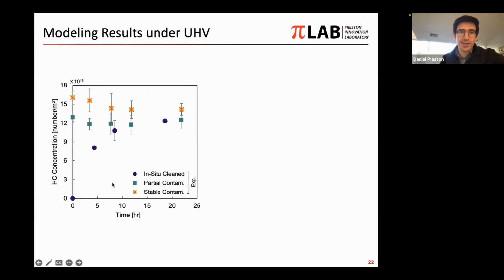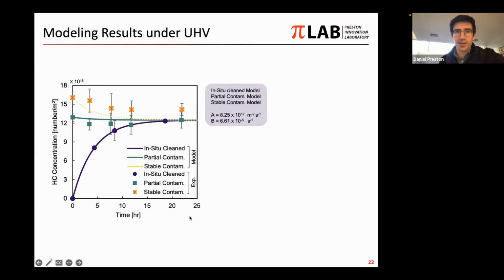And so again, showing the same data here, we started by taking that model and fitting it to our sample that was contaminated over time after initially being cleaned in the chamber. And from there, we were able to calculate these coefficients A and B for the model and use them also to try to explain the partially and stably contaminated surface evolution over time as well. Seemed like a pretty good explanation. We did not quite get down to the same low level of equilibrium with the stably contaminated sample. And so we also fit a different value of B, which we called B prime, to the data points themselves